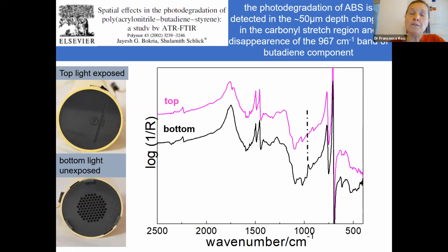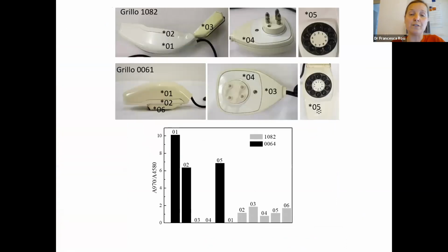Taking into consideration the different depth of sampling that we have by looking at the mid and the near infrared range, at this point we can also monitor and map the degree of oxidation of ABS, taking into consideration the band in the mid-infrared range of butadiene, which is sensitive to the degradation, to the decrease on the first layer of the polymer, with respect to the bulk information regarding the presence of butadiene in the near infrared range.